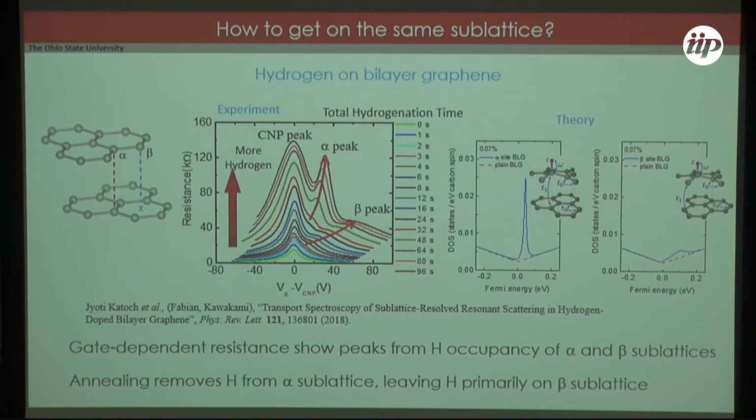Yeah. So actually, if you look really closely, the beta peak comes out first, even though it's smaller, and then you don't see the alpha one until a little bit further. The calculations say that the beta site should be a little bit more thermally stable than the alpha site. That's consistent when we're depositing, and it's also consistent when we desorb. And maybe I should ask Yarrow actually: what would control this shift in the theory? Do you have an idea?